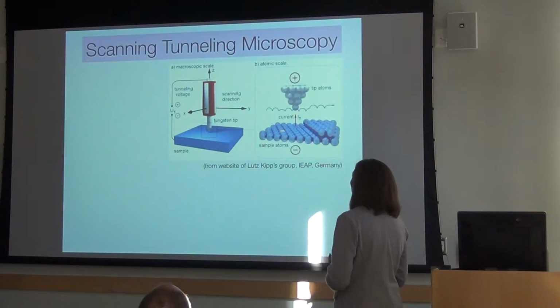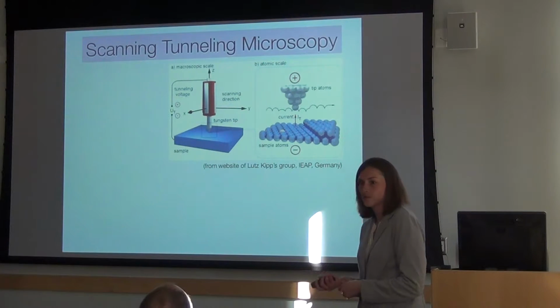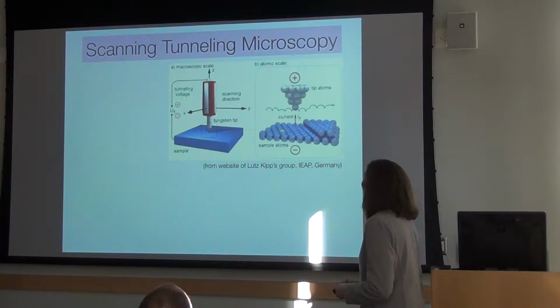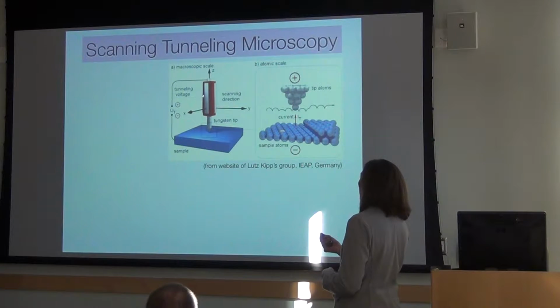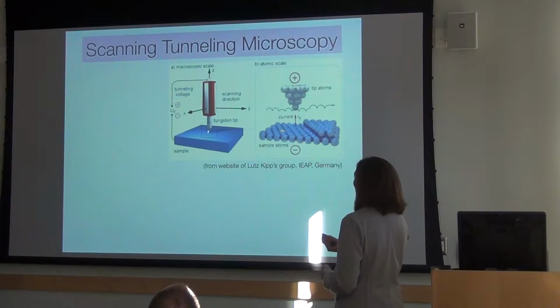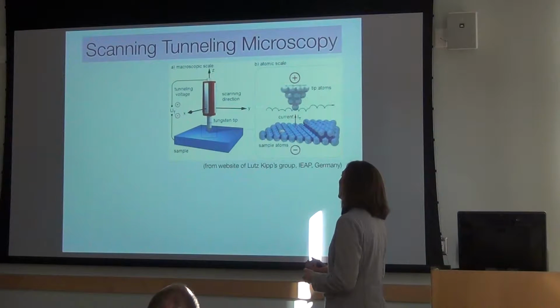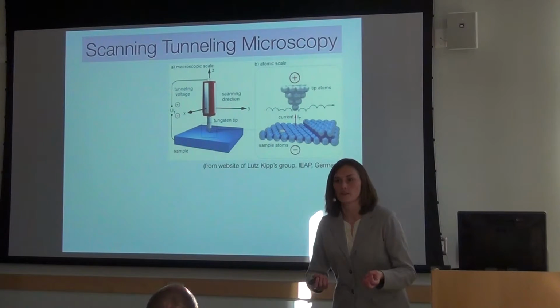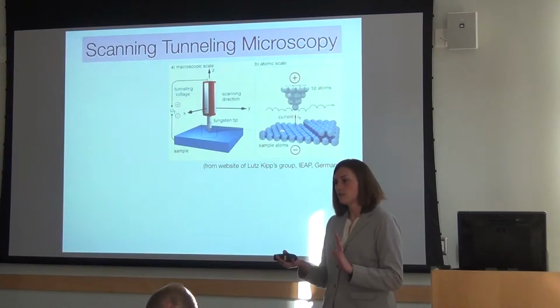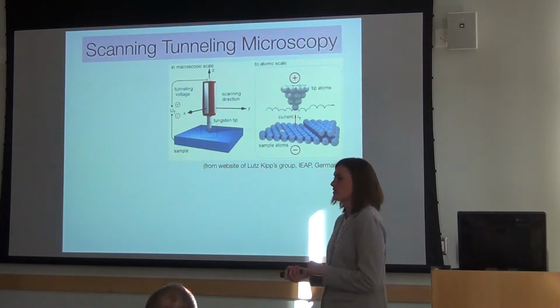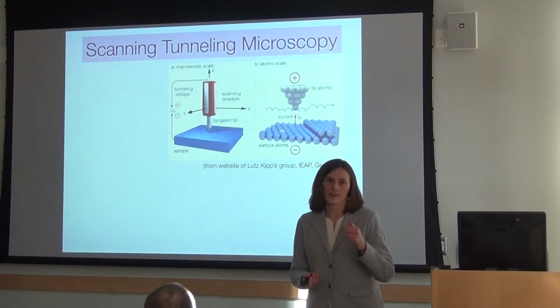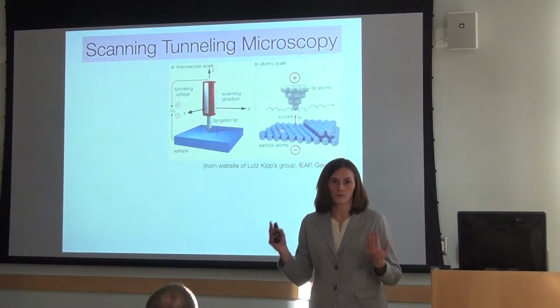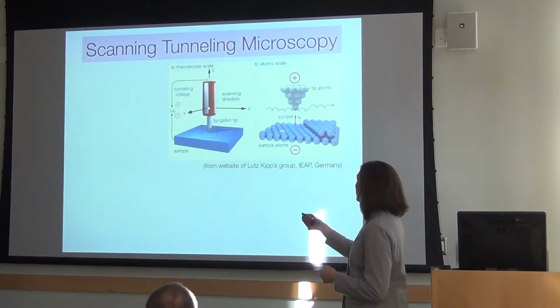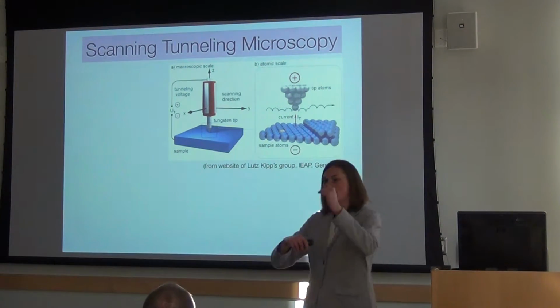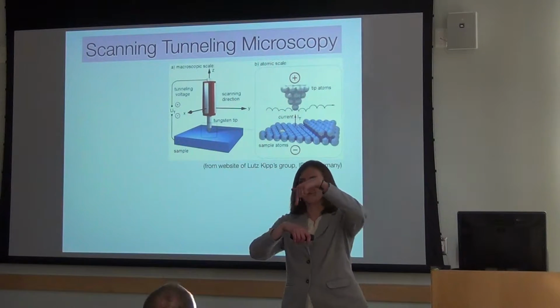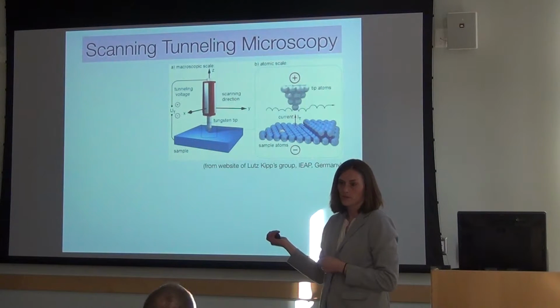Okay, so I wanted to take a minute to tell you a little bit about scanning tunneling microscopy. I'm not sure if all of you are familiar with this technique. On a macroscopic scale, you have a piezo, and you put a wire inside this piezo tube. A piezoelectric material is a material that deforms when you apply an electric field. This is how you are able to control the movement of a wire down to the atomic scale. So this really enables the whole technology of STM. You apply voltages on these electrodes on opposing sides, and that deforms the piezo so that the tip can do the scanning motion. So that's how the tip scans back and forth.